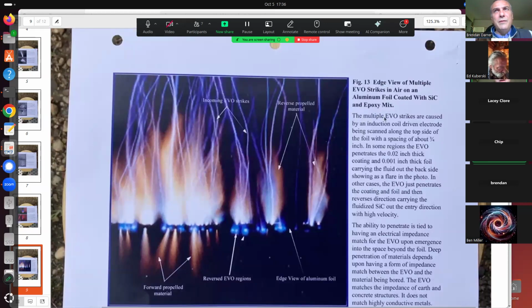The multiple EVO strikes are caused by the induction coil driven electrode being scanned along the top side of the foil with a spacing of about 3/4 of an inch. In some regions, the EVO penetrates the 0.02 inch thick coating and 0.001 inch thick foil, carrying the fluid out the backside, showing as a flare in the photo.